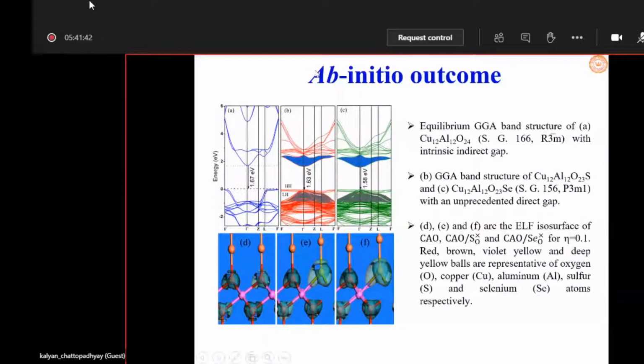But as soon as we incorporate some sulfur at the oxygen place, see the middle band structure. It is very interesting how the band structure got changed. You see here at the gamma point, the valence band maxima now comes. That means essentially the material becomes a direct band gap. Not only that, you see that along with the heavy hole band, a large number of light hole bands have also appeared. So this is very important for getting better electrical properties and higher mobility, as I already indicated. And also there is a significant increase of the density of states.